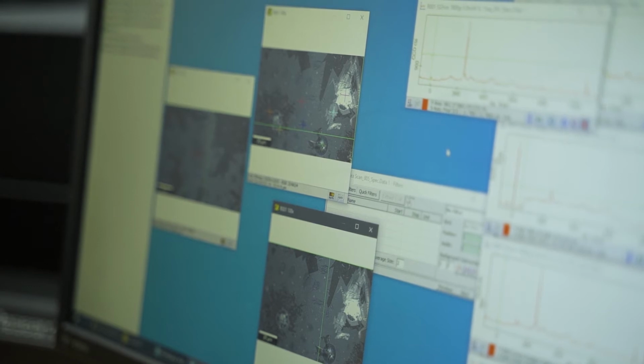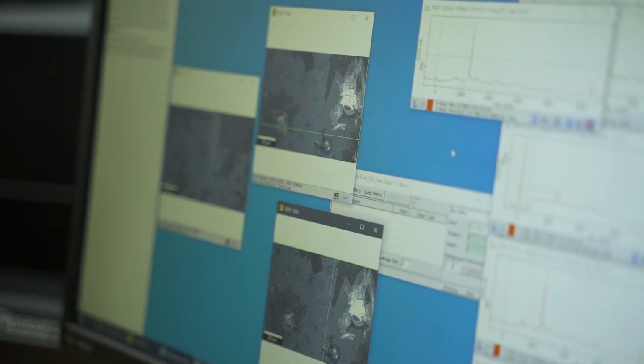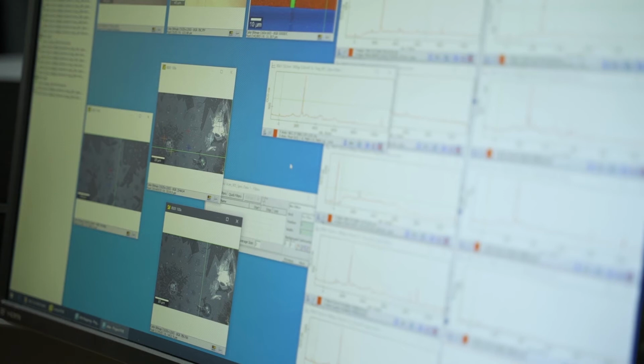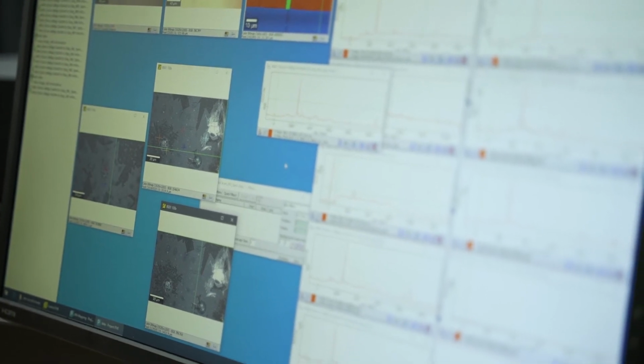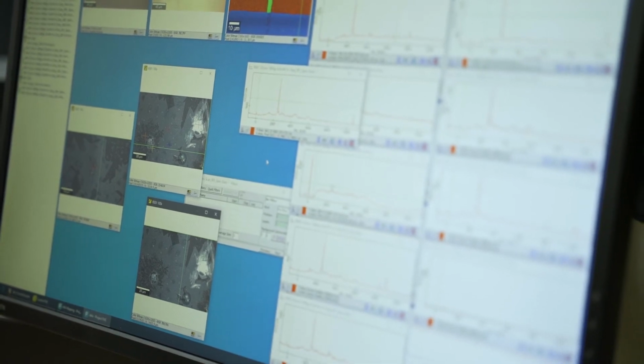We can also take out information on whether the sample is under stress or if it has some defects. This is very important because it will be the active material in the photodiode. Also with Raman, we can infer the sample quality, if it is good to go to the next steps or if we can do a different improvement in the growth. The sample can be characterized point by point or by making an area map, as is shown here on the screen. This is mainly what we do here.